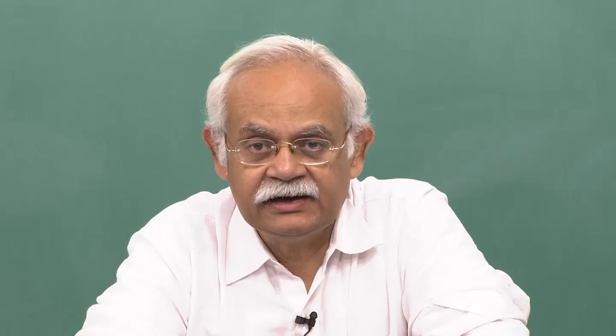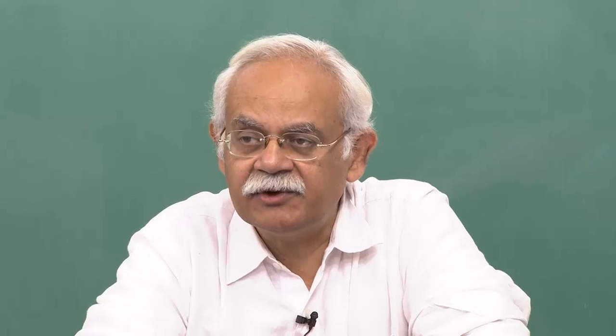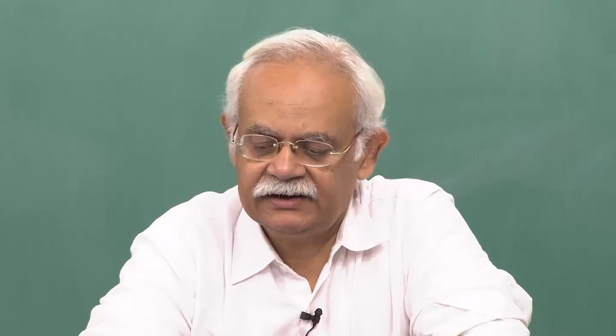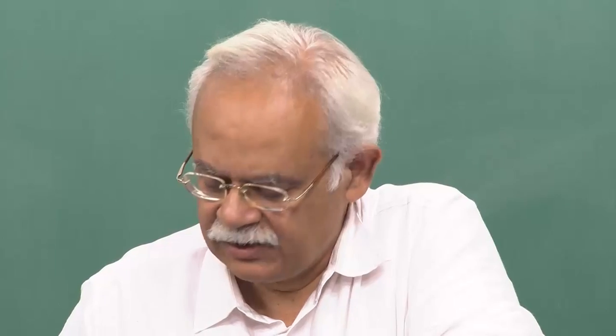So now if that doesn't happen, we must be prepared that once for some reason hydration stops, it will be difficult for any amount of strength gain to happen after that. So this is precisely what is being shown by this picture here. So while we are talking about in the laboratory, entire time in the air after 7 days of moist curing, or in air after 28 days of moist curing, or moist curing entire time, we can see that that makes a difference to the ultimate strength that is obtained.